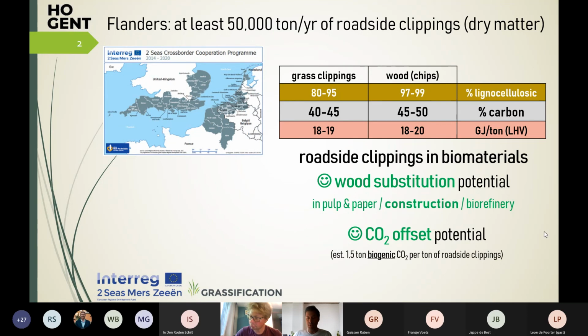Besides that, it stores carbon, CO2 from the air. We call this biogenic carbon. For each ton of roadside clippings, we estimate that about 1.5 ton of CO2 equivalents are stored in the raw material per dry ton. Compared to wood, that's about similar. Grass has a somewhat lesser carbon content, 40 to 45%, due to the higher ash content compared to wood. But in general, we can say that organic materials contain between 45 and 50% of carbon, if you exclude the ashes.